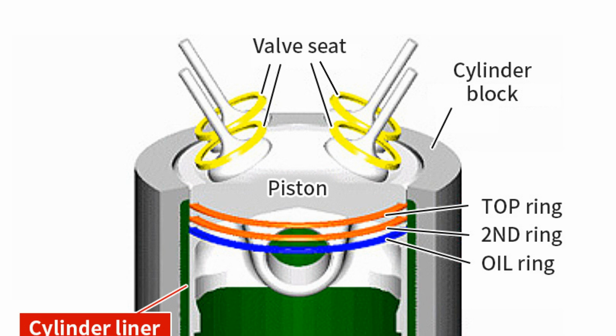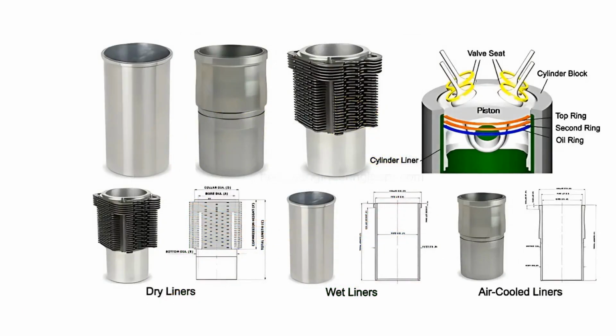The basis was an alloy of aluminum, where 17% silicon was added. To describe briefly, the mirror of the working cylinder was subjected to sharp and strong cooling, which allowed the silicon to crystallize. Then the area was treated with various acids. They removed the remaining aluminum at the molecular level. As a result, a high-strength solid wall appeared inside the cylinder, on which pistons with steel rings ran quite freely and without risks of damage. The technology seemed very promising, which led to its further development. As a result, aluminum sleeves saturated with silicon appeared.